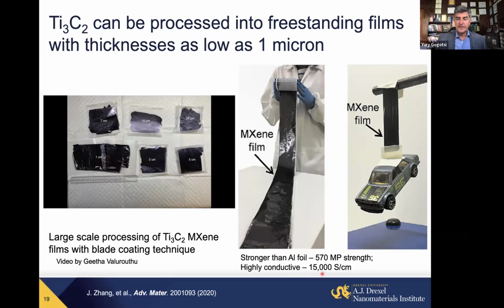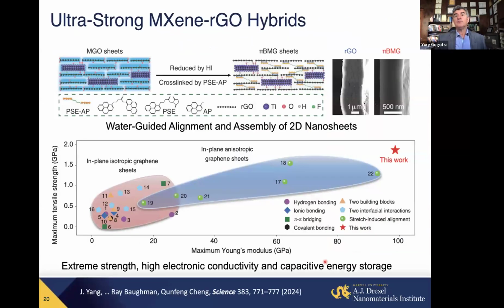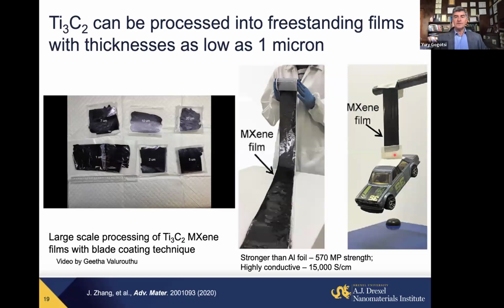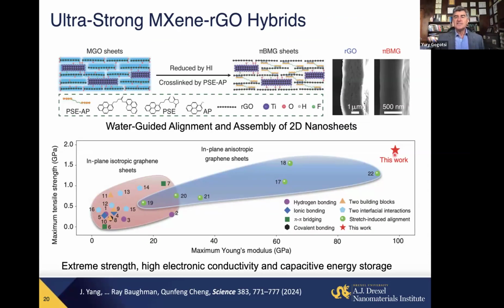It's also highly conducting. It's about 10 times more conducting than reduced graphene oxide, where you can, in a similar process, take graphene oxide, dry it, heat it up to 400 degrees C, remove oxygen, and you still will have much lower conductivity and lower strength. But moreover, if we combine graphene oxide with MXene and add some organic molecules to cross-link them, stitch them together, one can get a material, again very similar, a 1 micron, couple of microns thick foil with strength close to 2 gigapascal. This is twice the strength of steel.